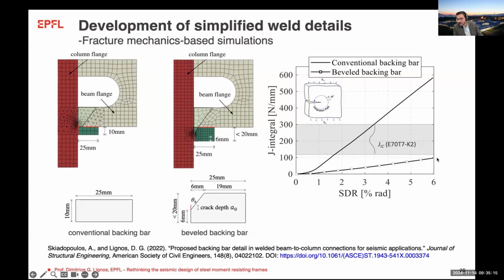And in this case it would be larger than 6%. And this is a pre-Northridge connection, okay? So we thought that this is actually promising, since the fracture potential for pre-Northridge connections would be reduced by 6 times by simply introducing a bevel in the backing bar.